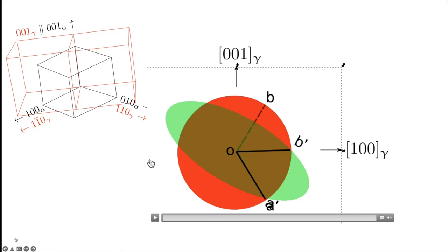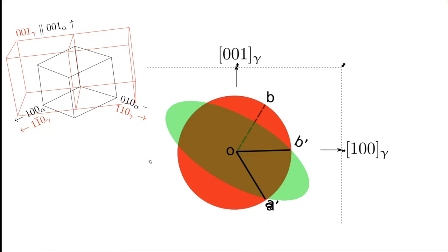although this rigid body rotation plus the Bain strain exactly predicts the observed irrational orientation relationship. So to calculate the expected orientation between austenite and martensite, all you have to do is apply the Bain strain and a rigid body rotation which brings a coherent line. And that precisely predicts the irrational orientation relationship that we observe between the austenite and martensite. This very, very simple calculation.